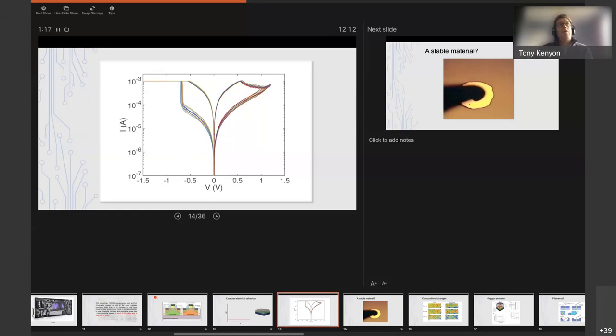Now, there are more exotic materials, in fact, almost any oxide. In fact, I guess if I say any oxide, if it's a solid, will show this resistive switching behavior. And many polymers as well. And there are various other ways that we can get resistance switching. So I've talked about the movement of oxygen, but we can, for example, take a very high quality oxide, not put loads of defects in it like we do, and diffuse metals in instead, and you produce a metallic filament. And you do that very easily with metals like silver and copper.